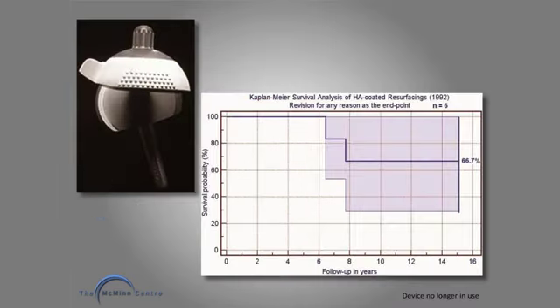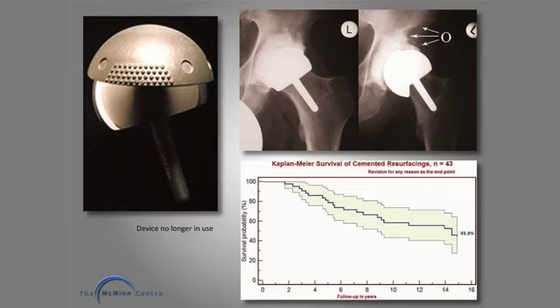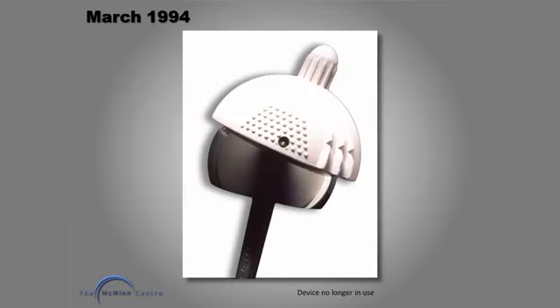I then carried out a small series of hydroxyapatite coating on the cup and the head, and the cups were excellent and still remain excellent, but the femoral components were not ideal, and in this tiny series, 2 of the femoral components loosened. I then tried cementing both the cup and the femoral component, and the femoral component was perfect with 0 failures, but the cup was terrible. Cemented metal cups had micro motion at the implant cement interface, generation of cement debris which caused osteolysis, and a very high failure rate. So from that little pilot study, it was clear to me that uncemented hydroxyapatite coated cups worked and cemented femoral components worked.